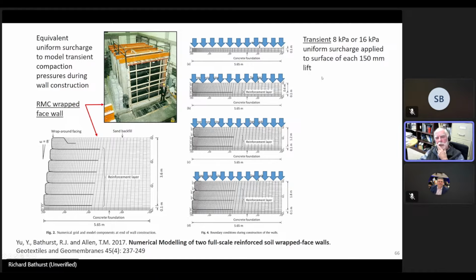And the technique that we came up with to handle the compaction effect was that at the end of placement of each 150 millimeter lift of soil, we applied a transient uniform surcharge pressure. And then when the layer was completed and before the next layer was constructed, we removed it, and then we repeated the process for the subsequent layers.